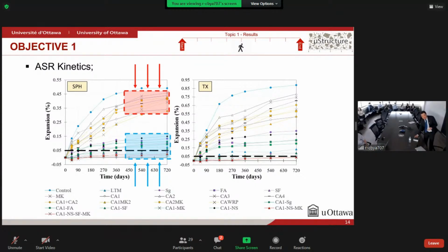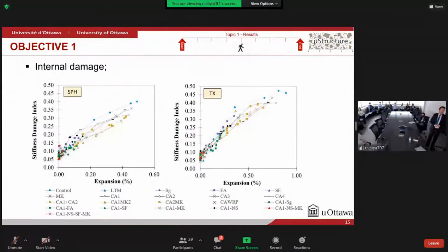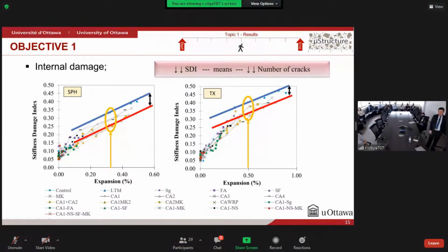So now let's see how they behave regarding the distress development. As we can see, through the stiffness damage index, in which we can have a good view of the internal damage of the concrete, we can see clearly that by adding crystalline admixtures in the concrete, we were able to decrease the SDI number for equivalent expansion amplitude, which means that the number of cracks and the internal damage of the concrete is reduced.